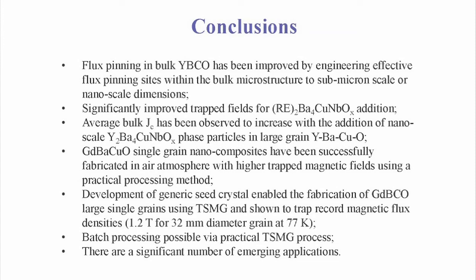Mike: On the types of material or defects that you can use for flux pinning in these materials? I think there are limits. I think the problem we have with our subject is that people get set in their ways, and they don't look where those limits might be. So different groups have looked at novel ways of making flux pinning sites on the nanoscale, from machining 211 for 3 days, to adding new materials, to looking at things like dislocations, some kind of lattice inconsistency.